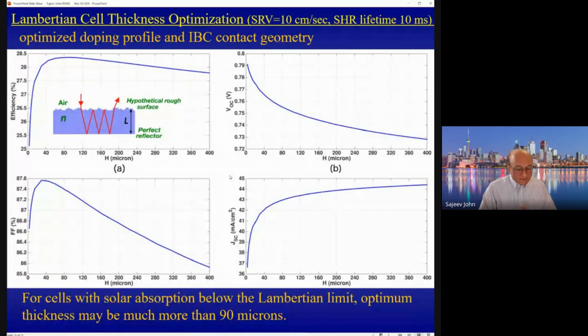Before I do that, let me ask what would happen in the case of a Lambertian cell, where we assume that light trapping is by ray optics only. So this shows what the efficiency of such a cell would be, as a function of its thickness. And here we actually assume a realistic state-of-the-art surface recombination velocity of 10 centimeters per second. We also introduce some losses due to bulk defects, which is described in terms of a Shockley-Read-Hall lifetime, which we take to be 10 milliseconds, which is essentially the state-of-the-art for the best quality silicon available.